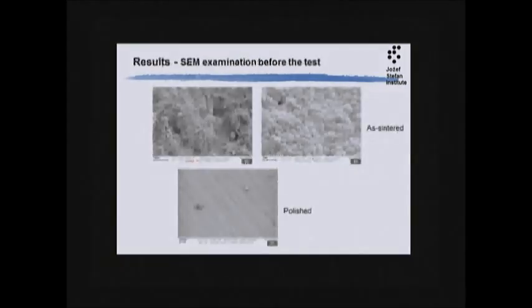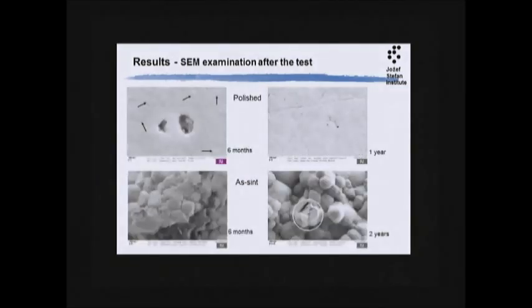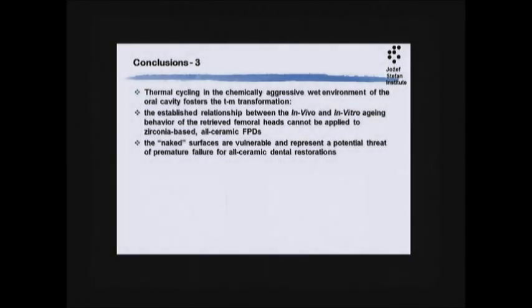Okay? And this is some microstructure. This was the surface, that it was rough. It's like you have after soft milling. And okay, after 2 years, that's interesting. You'll really see cracking of some grains will start cracking. But that's a good message. If you calculate the thickness of the transformed layer from the amount of the monoclinic on the surface, it roughly corresponds to a grain size, 0.3, 0.4 microns. It's not a thick layer that is transformed. And this is the message we have to take: we dare not just take the one relationship and generalize it for any material.